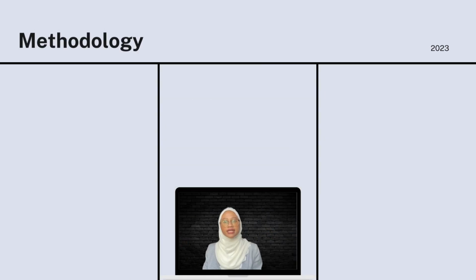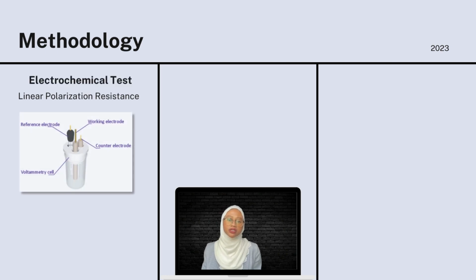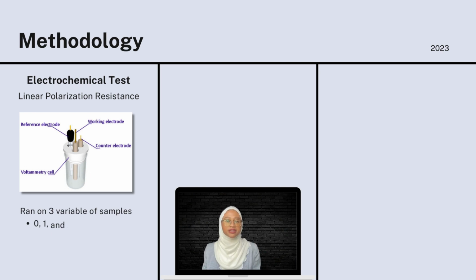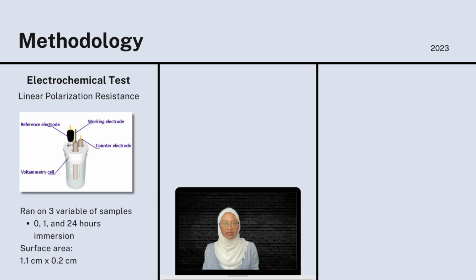The first part of this whole study was basically to determine the corrosion rate of copper after 3 immersion times in artificial sweat solutions using linear polarization resistance, also known as the electrochemical test. Silver chloride was used as reference electrode with platinum rod as counter electrode, and our samples, copper coupons, as working electrode, while the glass cell contained artificial sweat solution as electrolyte. This test was run on 3 copper samples that had been immersed in artificial sweat solution for 0 hours, which was as prepared, 1 hour, and 24 hours each.